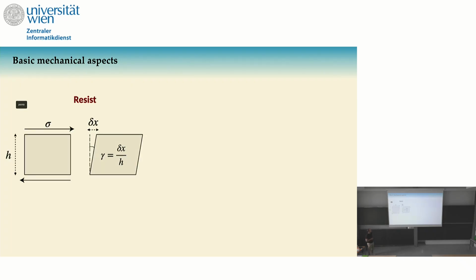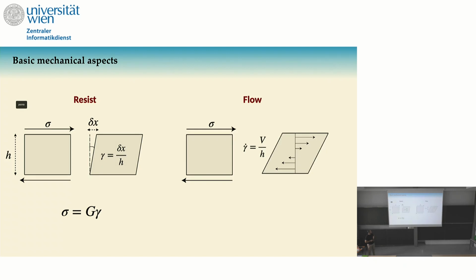So let's define what we mean by a liquid and a solid, just some basic mechanical aspects. If you start with a system of size h and you apply a stress or a deformation, delta x, then your strain would be just delta x divided by h. In this case, if you stop, the system would resist and go back to its initial form. The system is elastic. And then the stress is related to the strain with a shear modulus. Keep in mind, this can be generalized in tensorial form; I'm just talking about the non-tensorial expression. On the other side, if you have a system that flows, if you apply a stress or deformation, then your shear rate is simply the velocity that you apply divided by the size of your system. And at the same time, the stress would be related to the shear rate with the viscosity of your system.